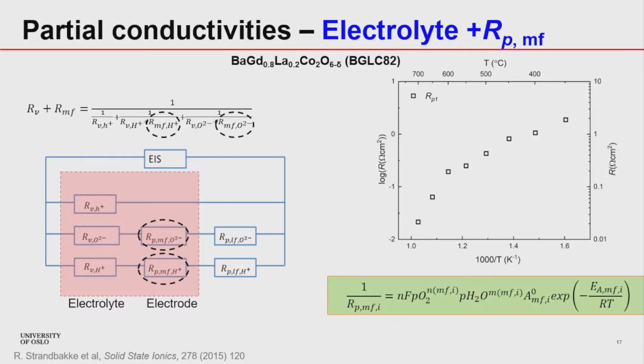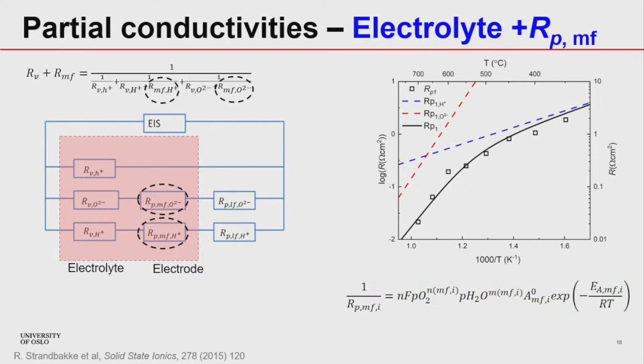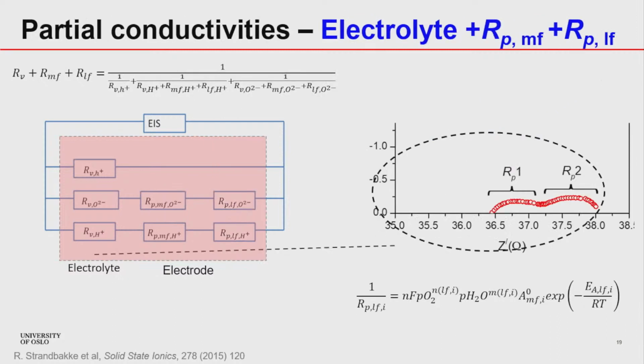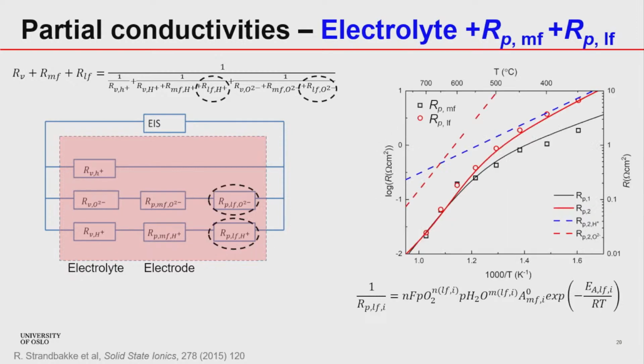So by using this model, we can fit the data and we can get contribution from the protons and oxide ions just for the mid-frequency process, and we can model the experimental data. Next, we can do the similar thing for the low-frequency process, and now we just need to fit the low-frequency resistances in the whole model, and we can again fit the low-frequency data for the protons and for the oxides. And by doing this, we can get the activation energies and pre-exponential factors from the modeling.